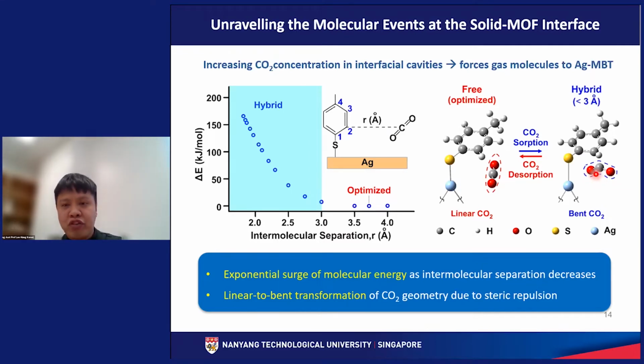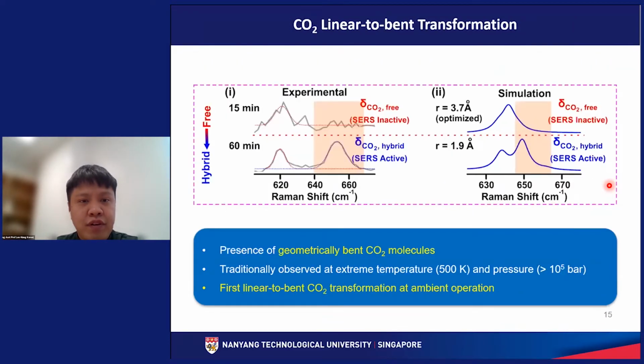This is mainly due to steric repulsion that causes the carbon dioxide to bend and also to elongate. This is very important because we want to identify the bent CO2 structure so as to confirm our theory. Subsequently, we compare our DFT simulated spectra with our experimental SERS spectra. What we want to confirm here is the presence of the bent CO2 molecule. The bending vibrational mode of our carbon dioxide molecule is usually Raman inactive because they are linear. They adopt a D infinity h kind of symmetry element. That is why the CO2 bending mode is usually Raman inactive. This is again indicated by our simulation, whereby we cannot see the CO2 bending mode in our simulated SERS spectrum.